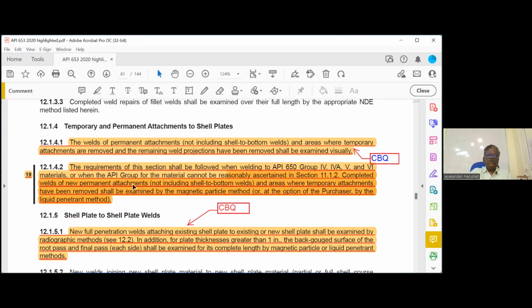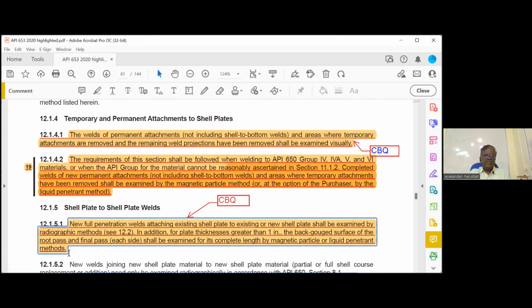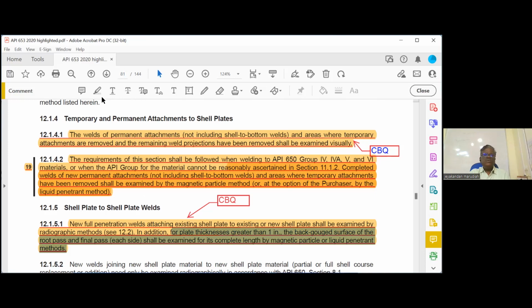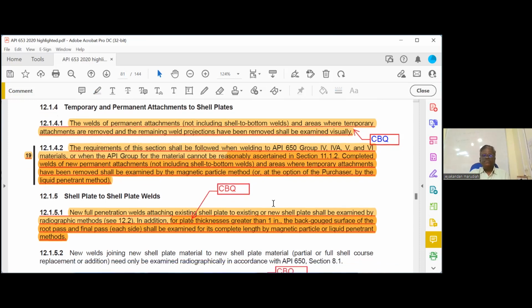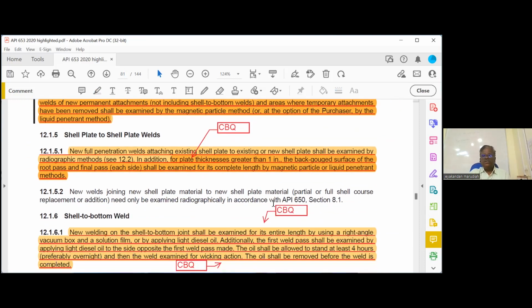Okay. Now, shell to plate welds. Radiography, they have given, I think, on the next page. But if the thickness is more than 1 inch and you are doing back gouging, all back gouged areas you have to do MT or PT. That is the additional. The next one, second line actually. For plate thickness greater than 1 inch, the back gouged surface of root pass and final pass shall be examined for its complete length by magnetic particle or liquid penetrant examination. That is important.